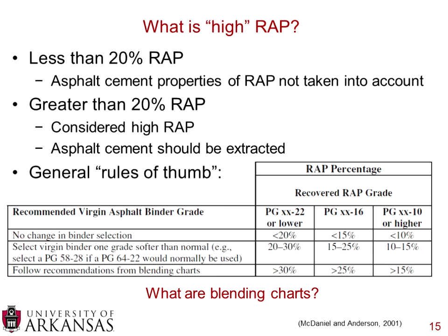And McDaniel and Anderson, this is from the NCHRP 452 report, they put together a nice little table with general rules of thumb. And you can see here that they have three different recommended virgin binder grades, a minus 22 binder, a minus 16 binder, and a minus 10 binder. And by showing your RAP percentage, you can say whether there's no change in the binder selection, if you're supposed to go one grade softer than normal, or if you're supposed to follow the recommendations from the blending charts that they put together. So you can see here if you're using, for example, a PG 58-28, and you are using 20 to 30% RAP,